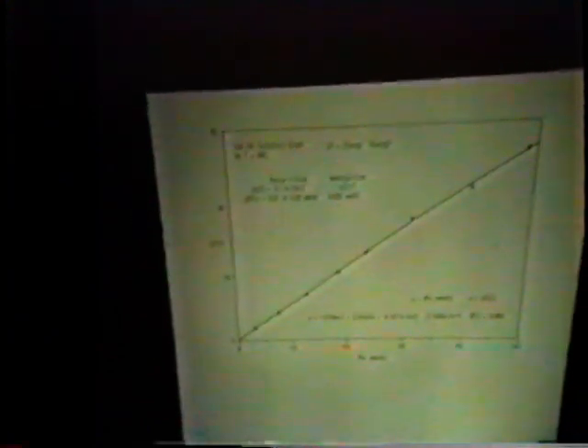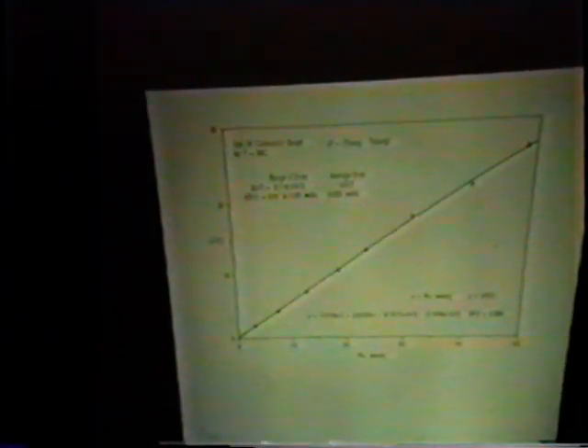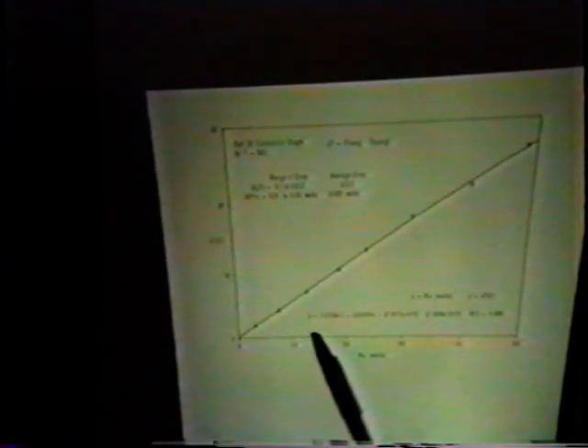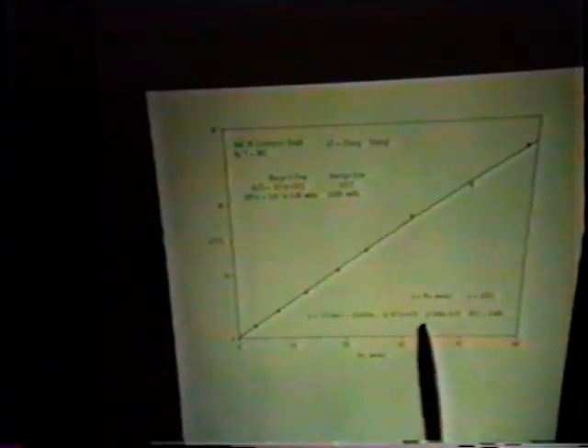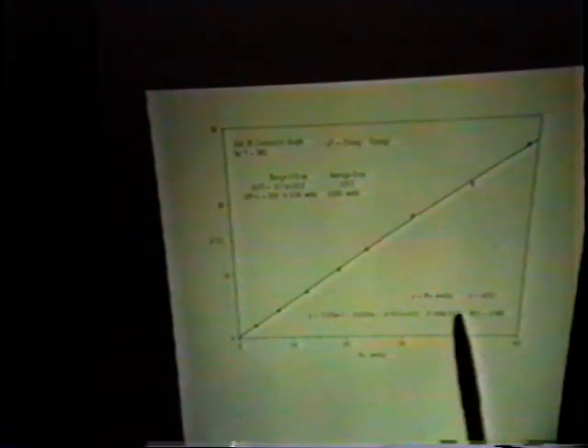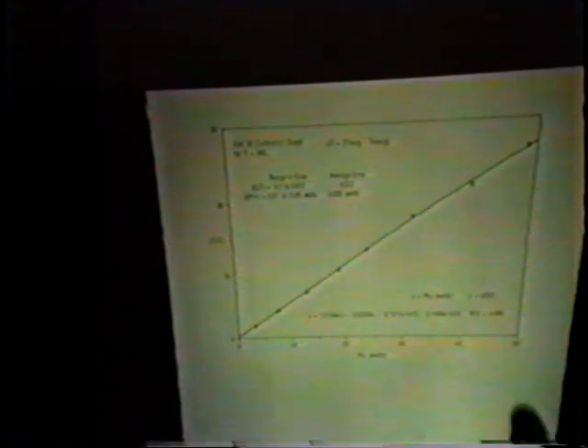This 60 micron one was relatively successful. This was the calibration curve. It looks quite straight, and in fact regression analysis was used to fit this to a polynomial. But it does look quite straight. The error bars would actually be within the squares on that.